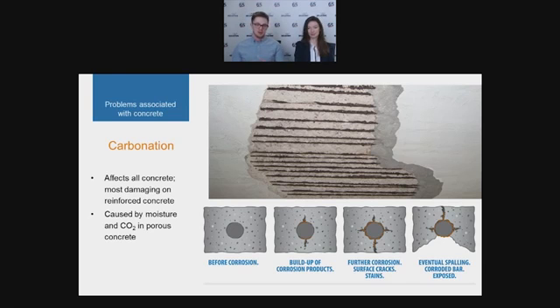If you lower this alkalinity and make it more acidic, you lower the pH level of the concrete, you tend to find that the passive layer disappears. And once this disappears, it's effectively like not having a coating anymore. That rebar starts to corrode, the rust expands inside the concrete, and exactly the same as the freeze-thaw damage and shrinkage damage, you get spalled concrete as a result. And this then exposes the rebar, which then causes it to rust further, and it's a vicious cycle at the end of the day.